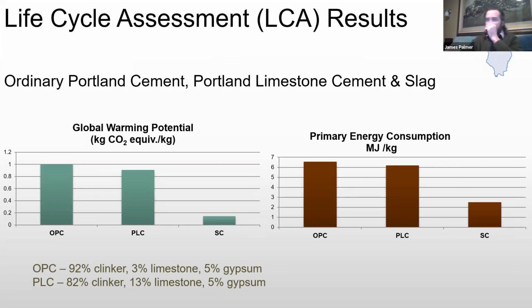And then this is just an example comparison of the global warming potential aspect of the life cycle analysis. As we said before, ordinary Portland cement, this is your type 1-2, you're typically looking at about 1 kilogram of CO2 per kilogram of the product, of which 60% is from the calcining. With the PLC, you see the 10% reduction.